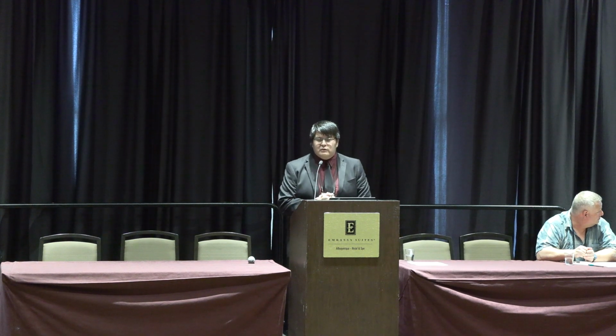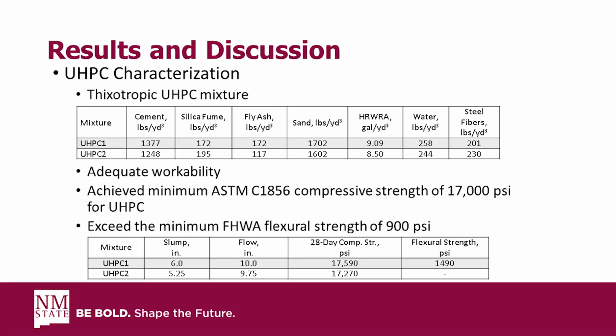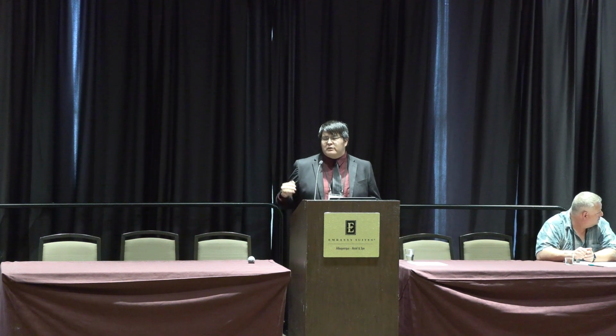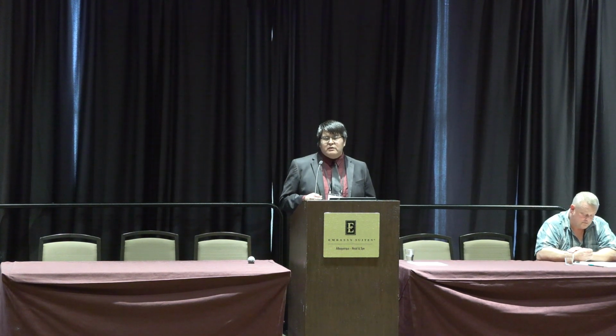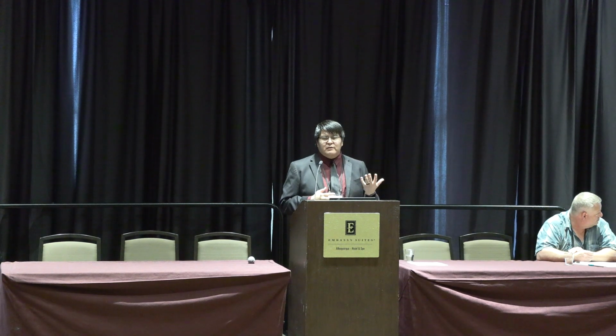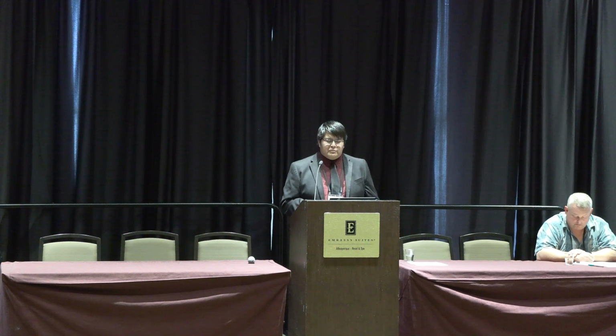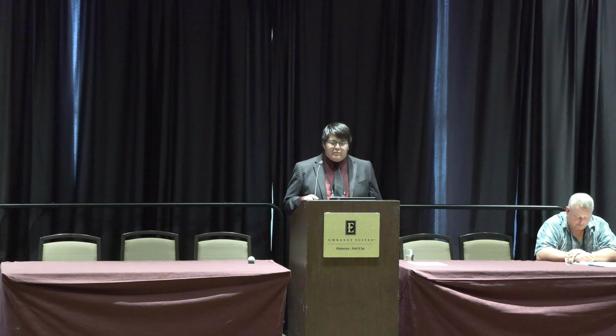Now we're going into the results from this study, starting off with the concrete characterization. And with the concrete characterization, we're starting off with the UHPC. So our UHPC mix is a thixotropic UHPC mixture. Thixotropic just means it's very viscous at rest and won't move until energy is put in to move it. So we wanted a thixotropic mixture just because we have no control on where we're placing this overlay system. If we place it on a sloped surface, we don't want it running off and accumulating at the bottom.